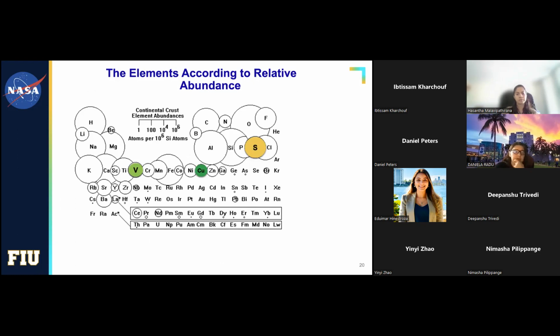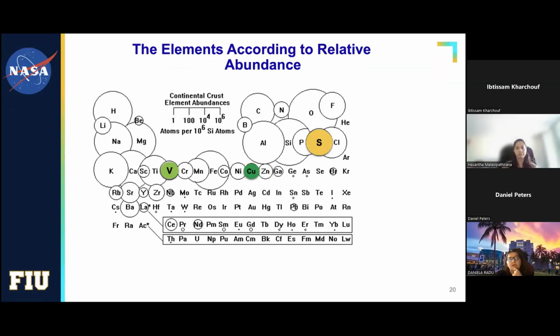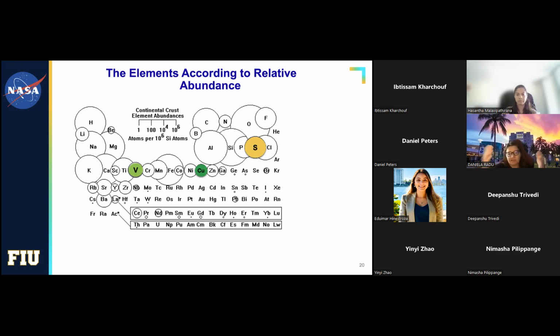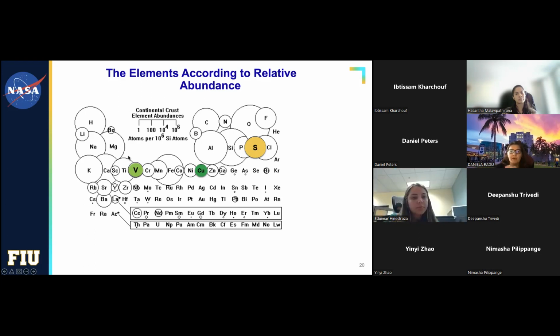Going back to my thoughts about relative abundance, we are still trying to get the efficiency as high as possible, and we are still in the quest for materials that can deliver that. And in this quest, we found a class of materials called sulvanites, which utilize copper, which is superabundant, sulfur as well, and one of the elements in group 5, whether vanadium, niobium, or tantalum. And to my surprise, when I first read about it, vanadium is actually one of the very abundant elements.